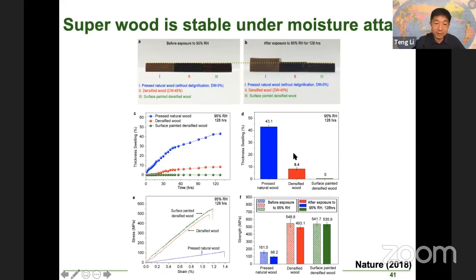You just buy this surface anti-water coating from Home Depot. You do a thin coating on it and then you do the test. It shows nearly nothing absorbed, the water absorption in the surface painted densified wood. And of course, the mechanical strength doesn't really decrease much.